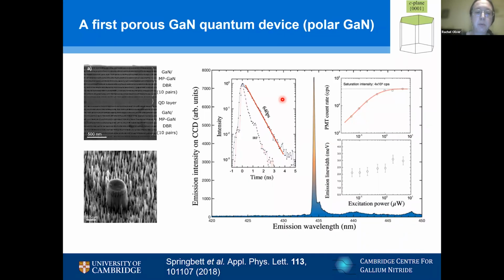So if we wanted to make, for example, cavity structures in low defect density material, but still with porosity, I would use ELOG GaN. Now epitaxial lateral overgrowth is a defect reduction technique. You get stripes of high defect density and stripes of low defect density. We would essentially use the defects to go down and then access the low defect density material, etching sideways. We'd have porous strips which had low defect density, and then ideally we could locate the cavities on those porous strips. Thank you. It's very interesting.